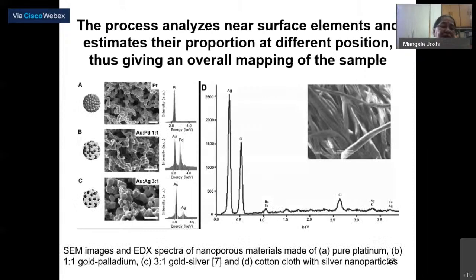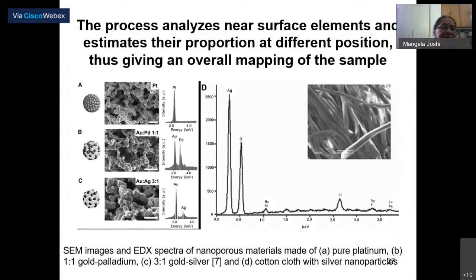If you can see the next picture, you can see the process analyzes near surface elements and estimates their proportion at different positions, thus giving an overall mapping of the sample. Now, on the picture, A is pure platinum. Pure platinum nanoparticles are there, so you can see the EDX peak shows only the platinum peak. Now, in the B sample, it is gold and palladium. So you can see these nanoparticles, and on the right side, you can see the image. You can see both gold and palladium peaks in the EDAX image.